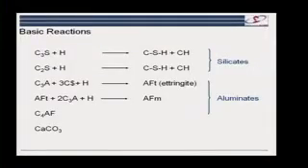And we're going to talk about half this session about this compound C-S-H. And why are we going to talk about half the session on C-S-H? Firstly, because it forms about half of the final microstructure. So it is the most important phase by a long way. But secondly, because it's not a nicely crystalline, well-organized material, its structure is still unknown on several levels. And its structure is also responsible for a lot of the complexity of the interaction of concrete with water.